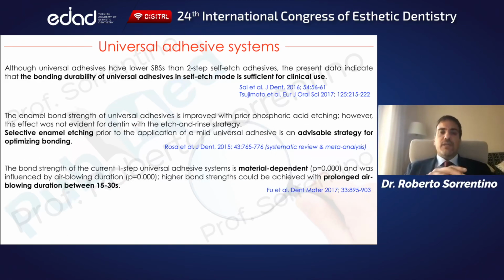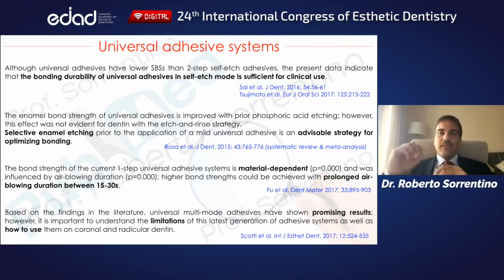It can be increased with prolonged air blowing up to 30 seconds to make the bonding layer very thin and uniform, and universal adhesives have shown promising results, but their clinical behavior has to be better investigated and understood in the long term.